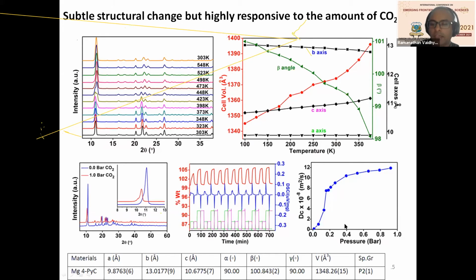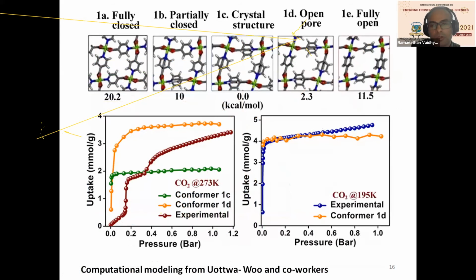And then by kinetic measurements, we are calculating the diffusion coefficient for the CO2, and we are able to see that it has a very favorable diffusion coefficient, or self-diffusion coefficient, for CO2, even though it is a very small pore MOF, but this is only after the gating has happened. Now, we resort to computational modeling with the help of a fantastic computational chemist, Professor Tom Wu from the University of Ottawa. We have been long-time collaborators with him, and he has helped us with some very, very crucial inputs in several studies of ours.